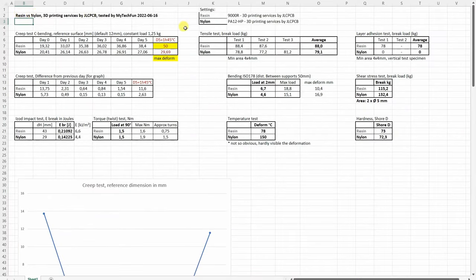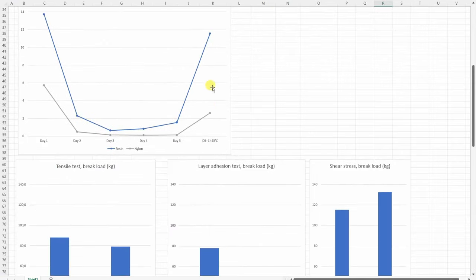These are all results in one table, which is downloadable from my website. This is the table for the creep test, and basically this is after the heating. I enter some numbers here so I can present it on a graph, but actually for the creeping I need the difference between 2 days, and that's why I prepared this table. So 0 means no creeping, and this will be presented in a graph. Here I have only 2 test objects, here 3 for the tensile strength, here basically only 1 for the resin. But let's see the graph.